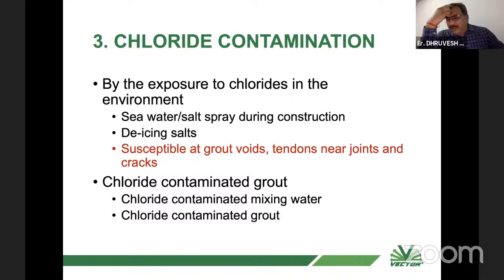You have chloride contamination. We come across various places, particularly in Mumbai or Chennai, where seawater is nearby. Grout is least cared about by people, and at the end of the job, nearly complete, a local laborer or semi-skilled person will be asked to mix cement and water and do the cement grouting. Although this is not the process everywhere, the water that has been used has hardly been tested. And if it is found to have a lot of chloride contamination, then it's a disaster. We have come across many sites, at least 4 places, where this has happened. This chloride contamination in grout may be because of contaminated mixing water, or the grout itself has chloride contamination.